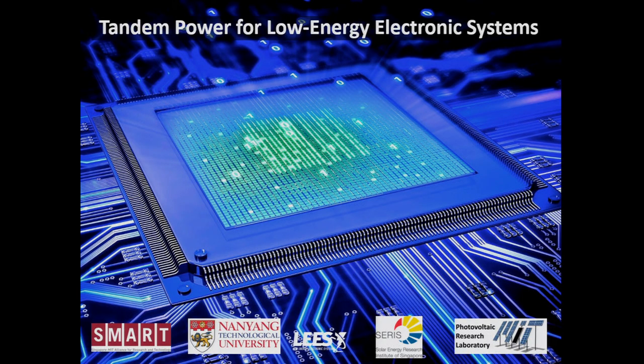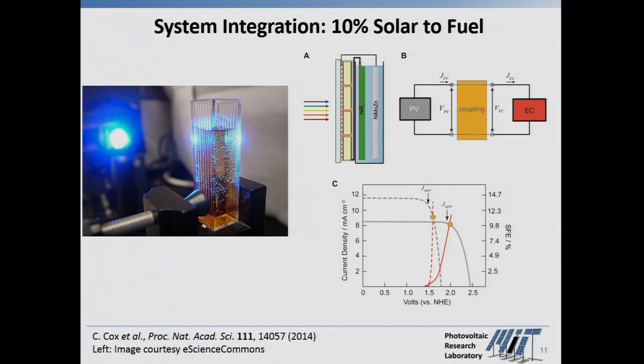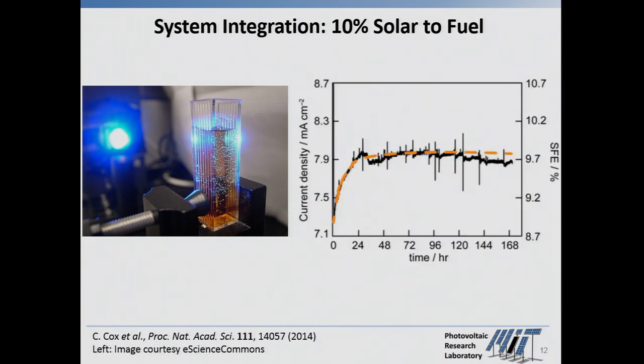So what can you do once you have these high-efficiency cells? You can begin exploring other integrations. How about coupling them with power electronics, with communications, and seeing what we can do as these component costs are being driven down by Moore's law? We can couple with storage, and we've done that successfully with a solar-to-fuel collaboration, in this case, with Dan Nocera, who's now at Harvard, by coupling the photovoltaic device directly to the electrochemical device without power electronics in the middle. Through good circuit design, you're able to achieve a stable operating efficiency of around 10% solar to fuel conversion with all earth abundant compounds. And this was demonstrated last year in 2014 with silicon devices.